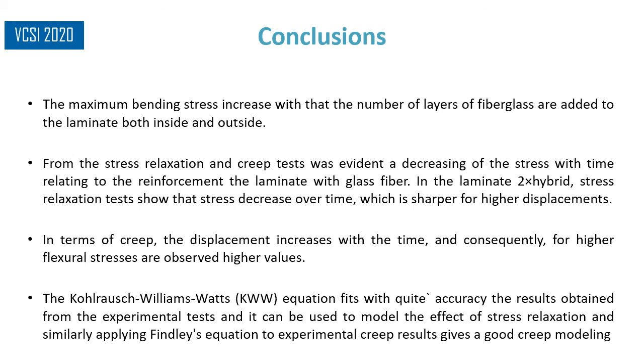The KWW equation fits well the results obtained for the experimental tests, and it can be used to model the effect of stress relaxation, and similarly applying Findley's equation to experimental creep results gives a good creep modeling.